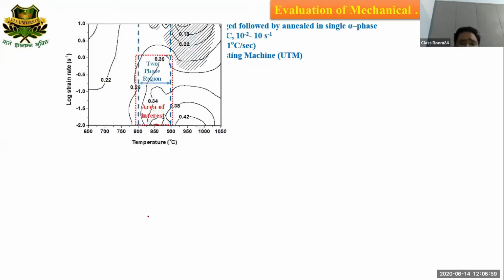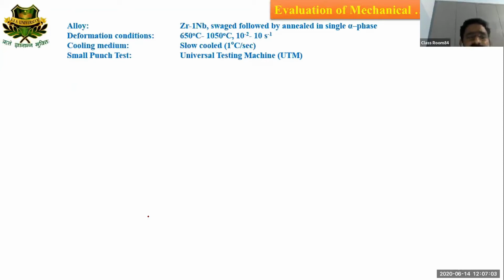So what we have done? We have made a small punch test to know the mechanical properties when we have the deformed sample. Here we are again considering zirconium 1 niobium alloy, but the as received condition is a little different. That is the swaged followed by annealed in single alpha phase. Deformation range is 650 to 1050 degree centigrade with some interval of the temperature. 10 to the power minus 2, 10 to the power minus 1, 1 per second, and 10 per second were the strain rates. We have controlled the cooling rate at 1 degree per second within the Gleeble system, known as controlled cooling.